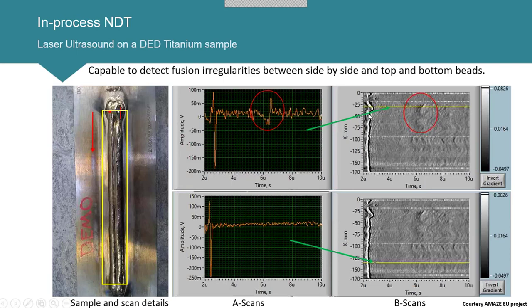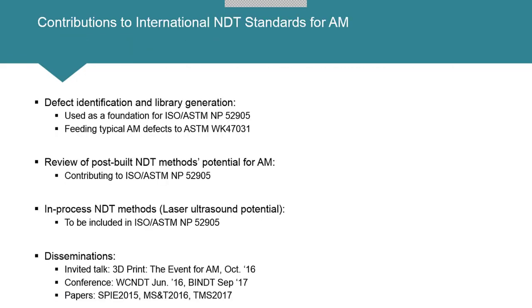The scanning is from top to bottom, and so this area here has a large effect on the delay in the Rayleigh wave. This is the surface Rayleigh wave, but there are also some features here which are, I believe, due to deeper defects, which I presume are possibly porosity or lack of fusion between the top and bottom beads, or top bead and the plate. And this shows a large difference between when there's a defect and when there's no defect on the A scan. So this laser ultrasound system is showing capability for both powder bed and for the potential for in-process inspection.